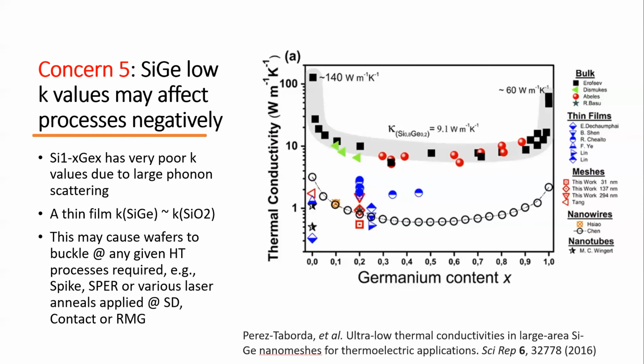And what are the other concerns? Oh yeah, there are. SiGe has a low K value. If you look at this one, this is pure silicon, and germanium content is on the x-axis, up to pure germanium. Pure silicon thermal conductivity is 140 watts per meter Kelvin. Decent, pretty good. And then germanium is not that good at 60, say one half, one third of it. Not too bad. But if you alloy them, it quickly drops down in a bell shape, right? It quickly goes to 10, 9, 10, when you have even 20% germanium.